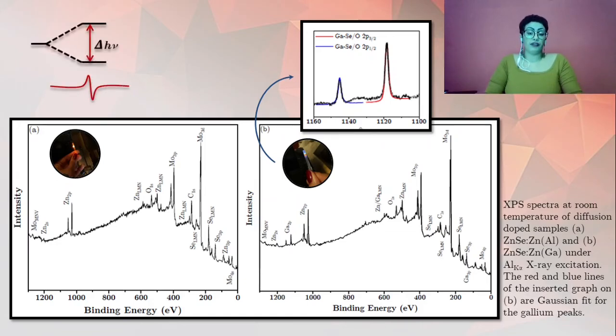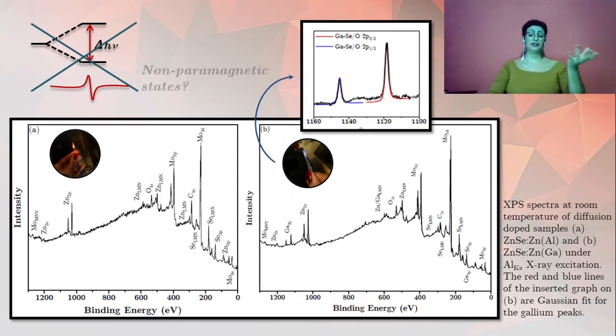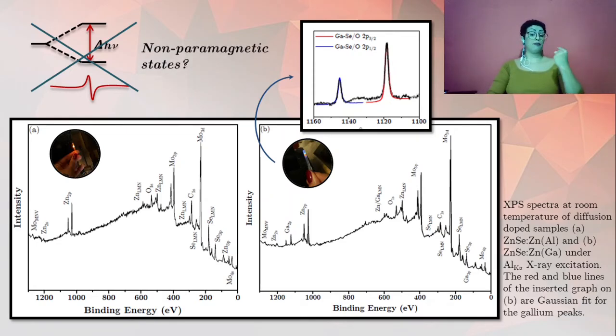EPR measurements were also performed, but no spin resonant transitions were observed. It was expected that the luminescent doped samples would present an EPR signal related to the A centers, since the characteristic luminescence in the yellowish-red spectrum region of zinc selenide is associated with the paramagnetic states of complex defects, and they will be present in significant concentration in the luminescent samples. However, the non-observation of an EPR signal, even in luminescent samples, may suggest that the luminescence of the material can be originating from the radiative recombination involving the non-paramagnetic states of these defects.